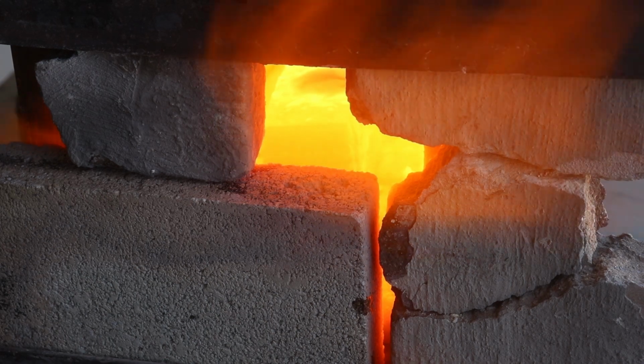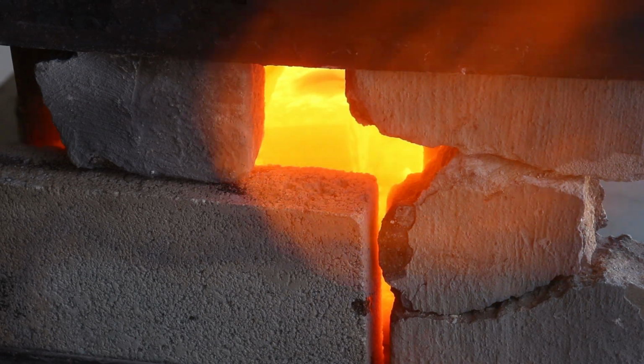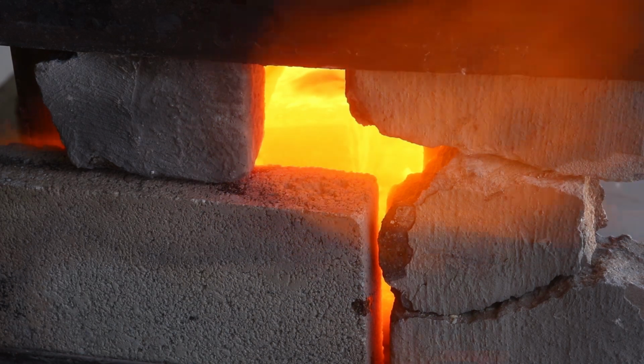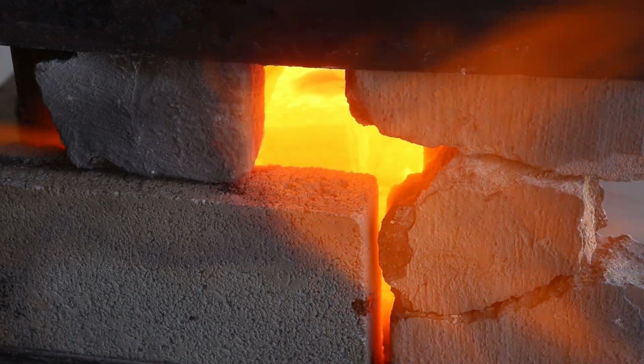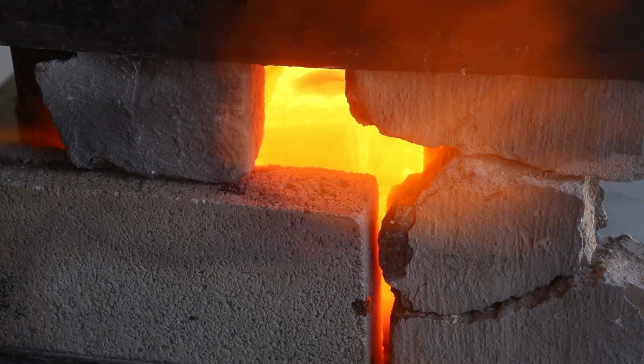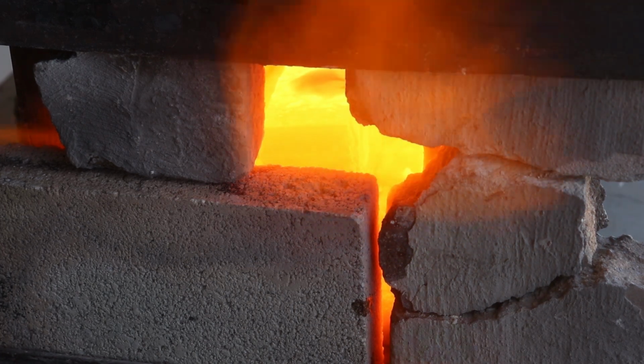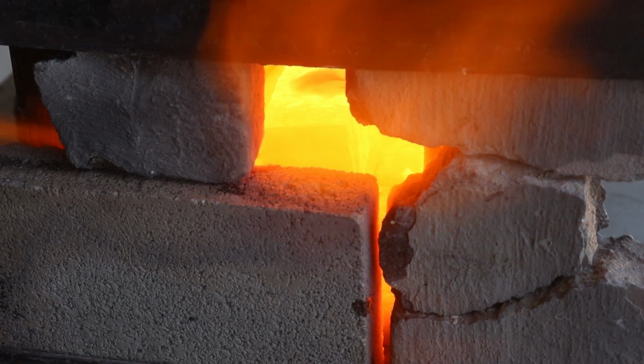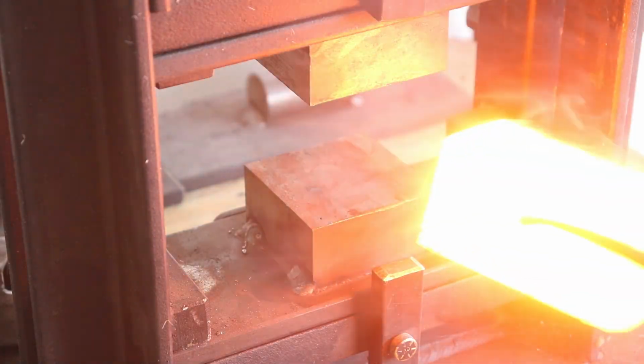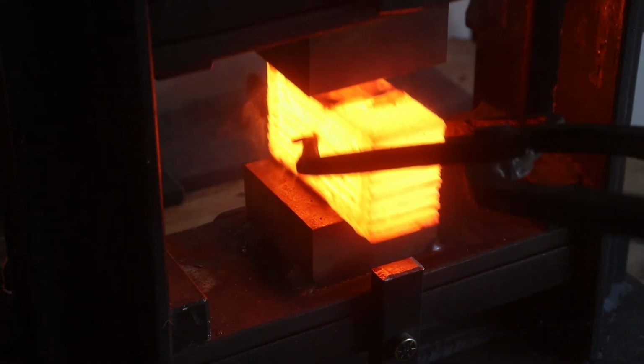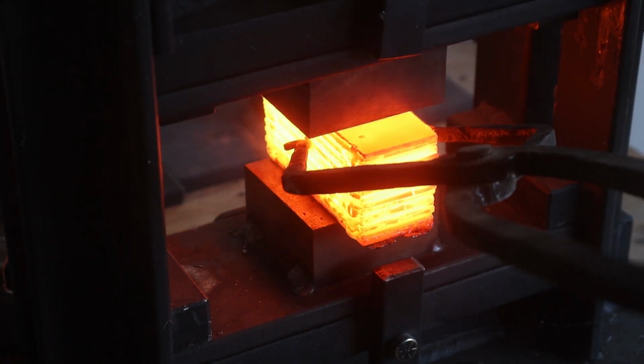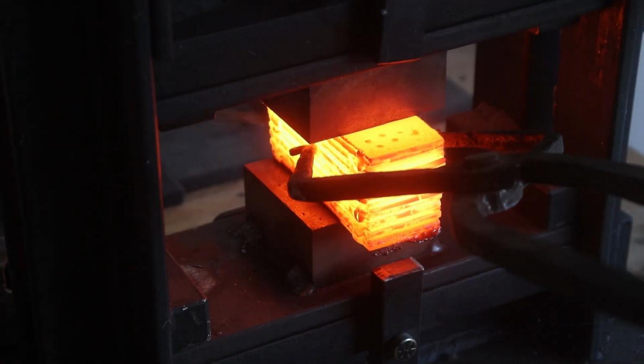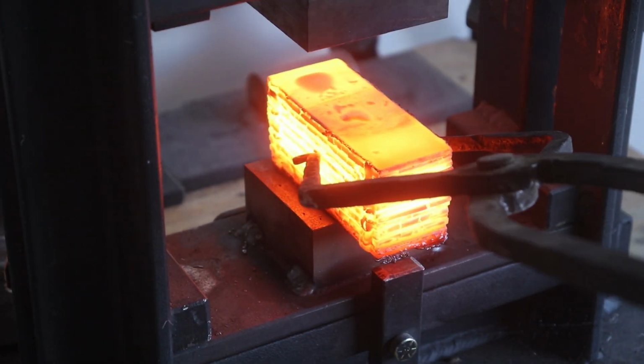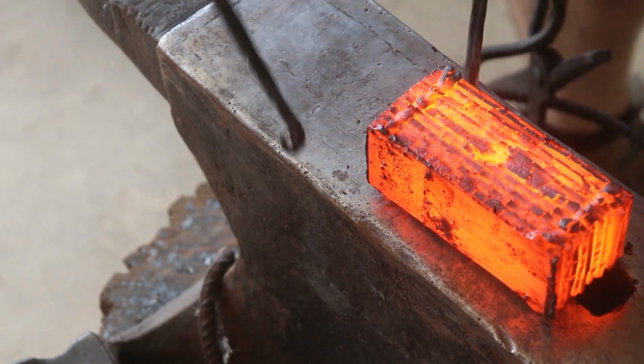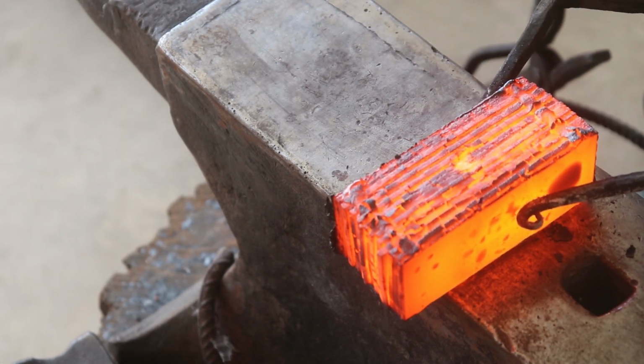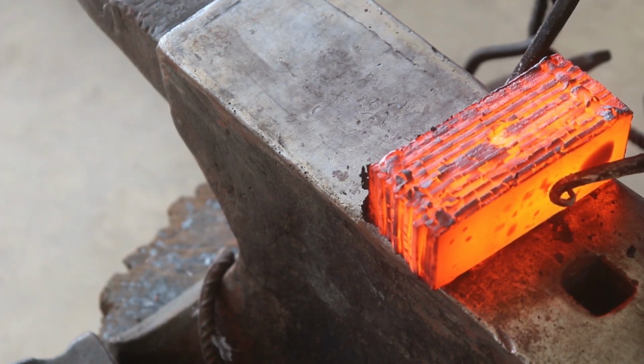Now you can see that the billet is the same color as the rest of the inside of the forge, which is a good indication that at least the outside of the billet is up to temperature. So at this point, I'm going to go ahead and start my soak. 6 or 7 minutes from now, I'll pull it out and just barely kiss the dies on the press to make sure everything gets stuck together without destroying the billet. Brush off all the scale, hit it with a little bit more flux, and toss it right back into the forge for another welding heat.